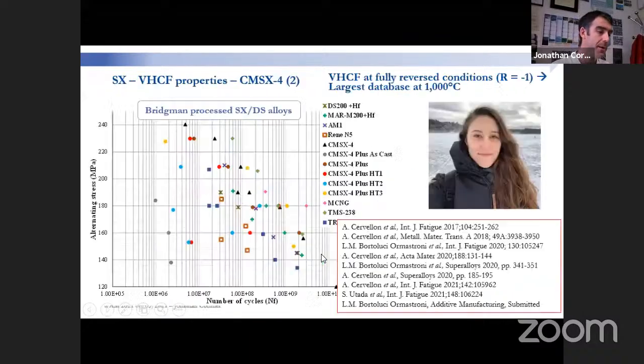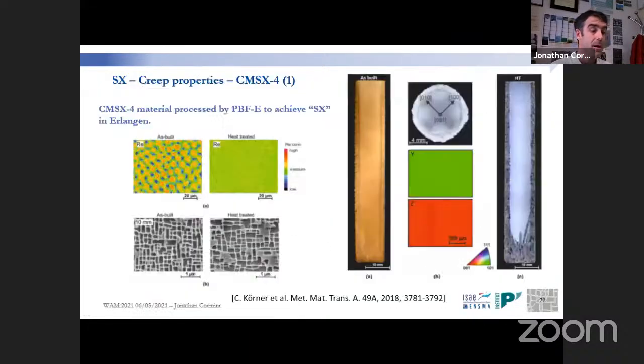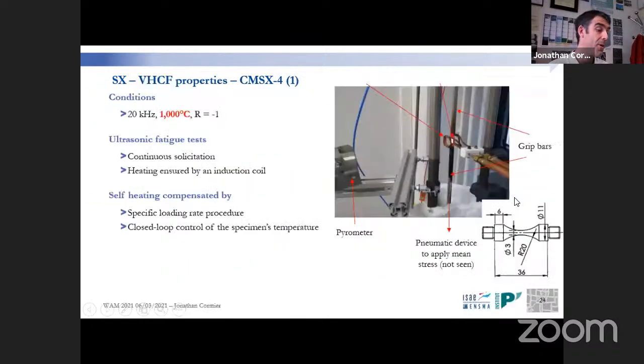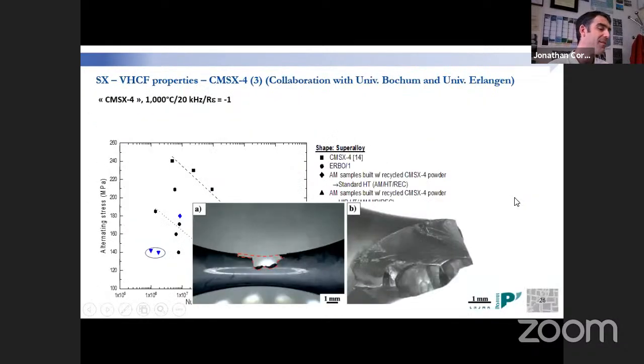I just want to go back a little bit earlier. You can see that here in those blanks, we have polycrystalline shells around, and when we do a heat treatment or when we add a HIPing stage, we may have a growth of this layer up to areas from which we are removing our VHCF specimens. And from this, we can say that the VHCF test is really a killer test because we have almost immediate failure.